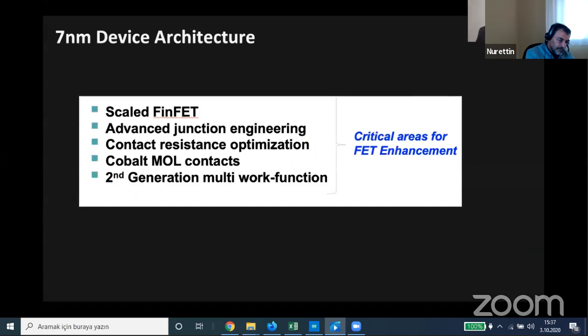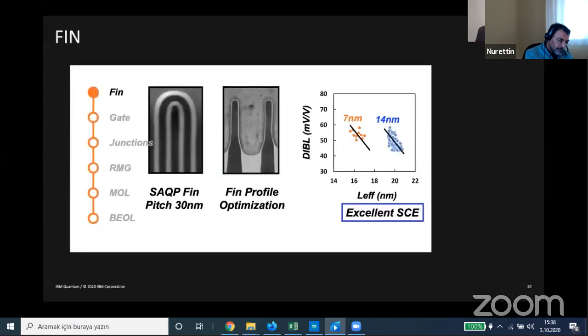To achieve those kinds of high ring speeds, we had to improve the device architecture through scaling the fin, advanced junction engineering, contact resistance optimization, introducing novel cobalt contacts in the middle of the line, and introducing a second generation multi-work function that enabled undoped fins and hence high mobility fins.